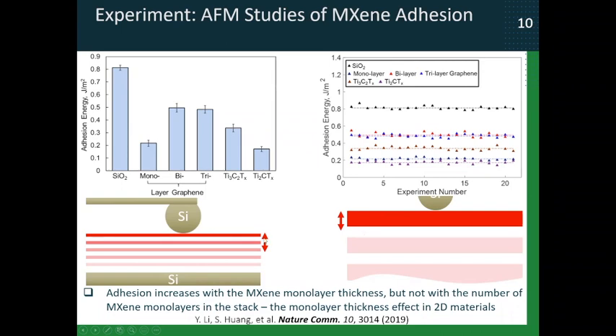graphene. And it turns out that if you calculate the length over which this additive effect on adhesion force propagates in graphene, which is shown schematically by the length of this arrow, then if you apply that same length for MXene, it turns out that this length is completely covered by just one monolayer of titanium 2C. And then it doesn't matter what you have beneath this monolayer, your tip simply cannot feel the effect of these monolayers beneath because the distance is already too much, even with one monolayer. So that was our explanation for the absence of this number of monolayers effect.